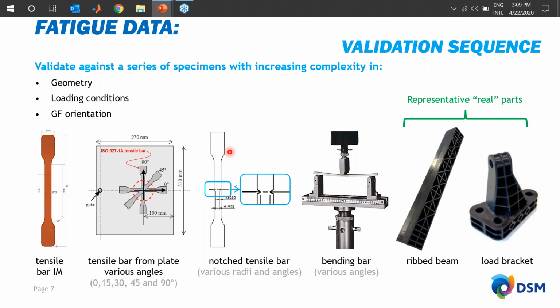Then from the same plaque, we also mill tensile bars in which we introduce a certain notch. And instead of only introducing various notch radii, we are also able to vary the fiber orientation combined with the notch radius. With that, we introduce a different stress state, so we can again study whether we can predict the fatigue life of such an intermediate part with a slightly more complex stress state. The same thing holds when we cut beams from these plates that we use for 3-point bending. Then we again introduce a different stress state that we can study as a function of fiber orientation.